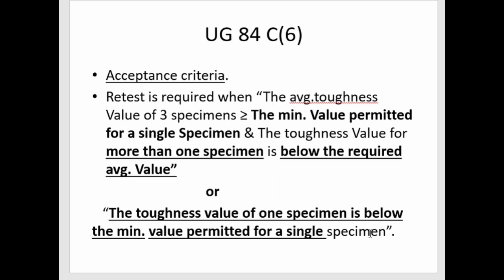A retest requires an additional three test coupons, and the toughness value of those three coupons shall be greater than or equal to the required average value. That means for retesting, the acceptance criteria become more stringent.